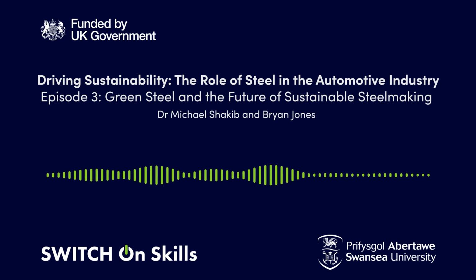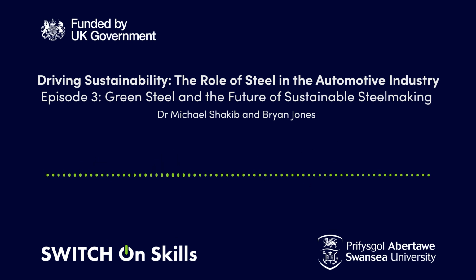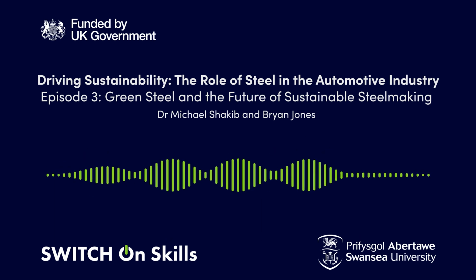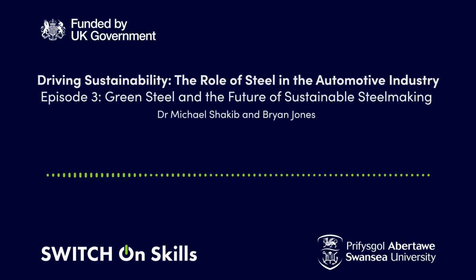So all of those processes will produce a steel which is still not high quality enough for automotive. So it needs to go through another process. Yes, because it's very much like the hot metal you generate from a blast furnace. So then that goes into the electric arc furnace, in which we add scrap. Yes. So the amount of scrap that you would add is dependent on the final application. If you're making something with a challenging application, you'd use less scrap and more directly reduced iron. Because you're obviously adding to the cost when you're using direct reduced iron. So 100% scrap is obviously the cheapest route. But there are major limitations in the use of many scrap products.